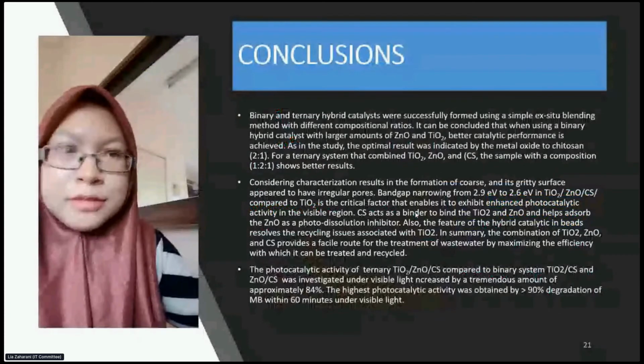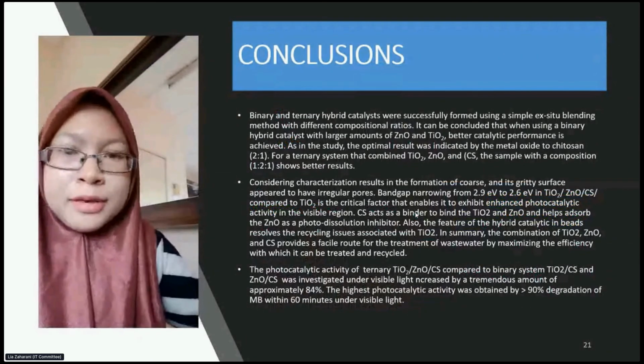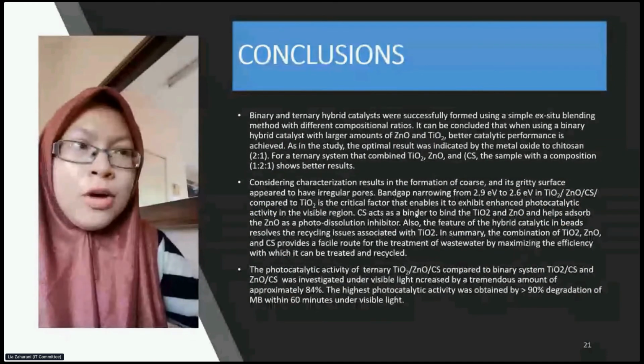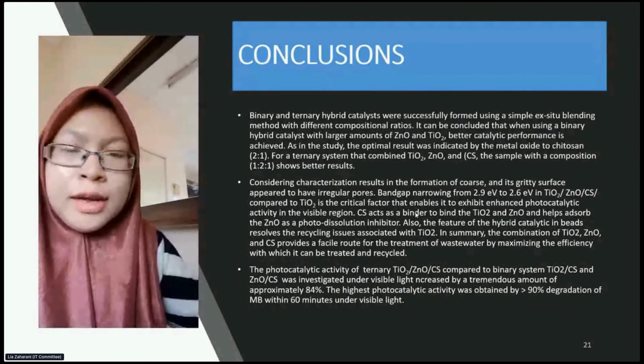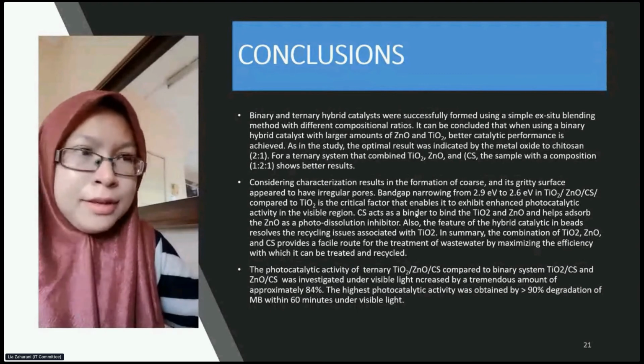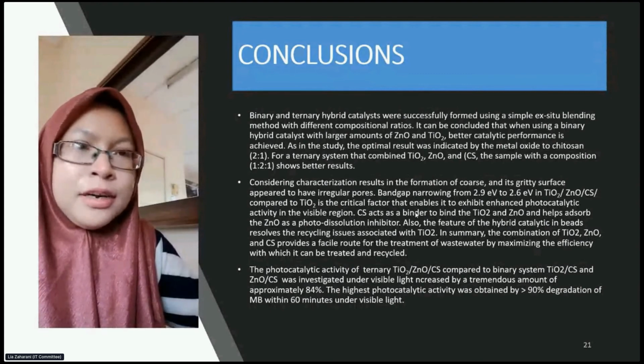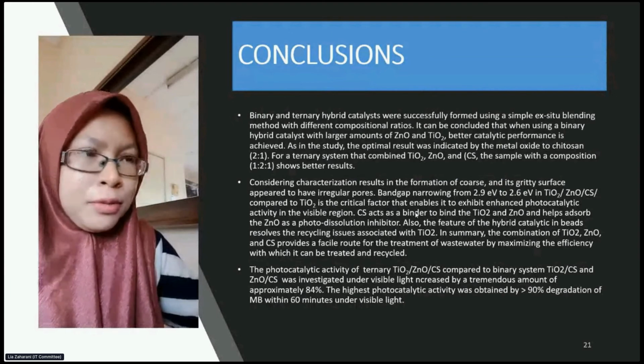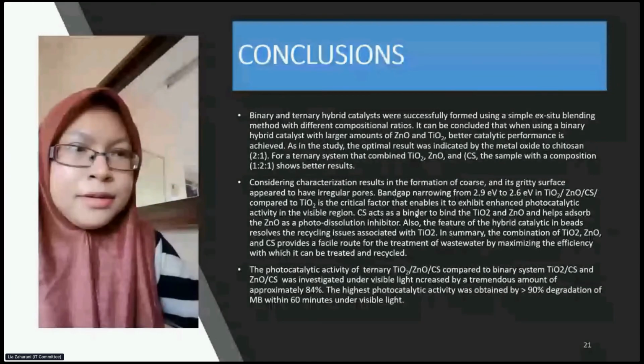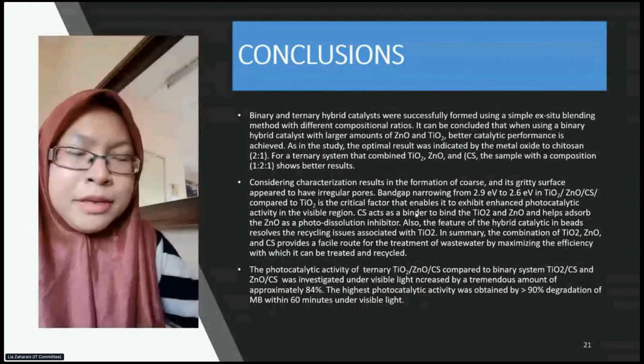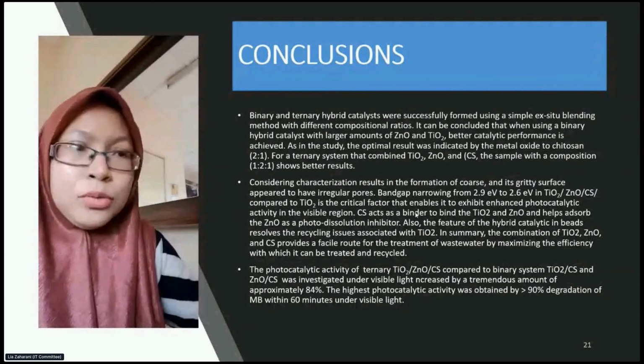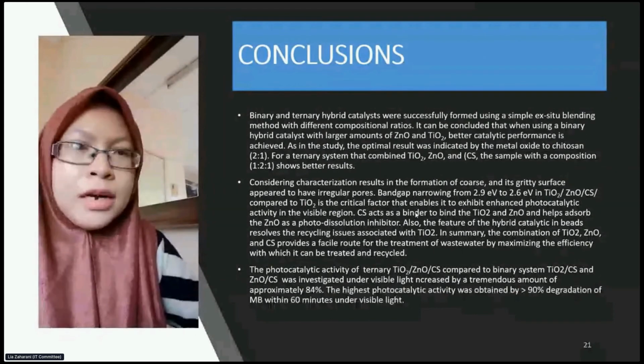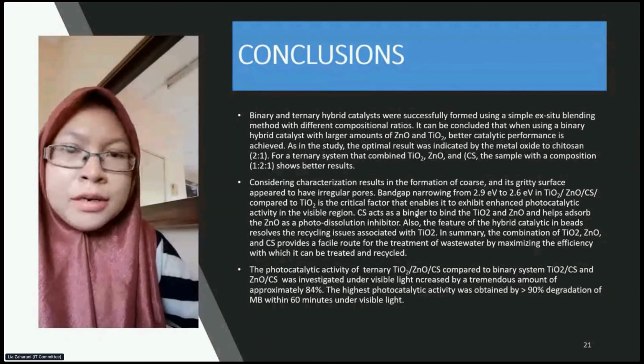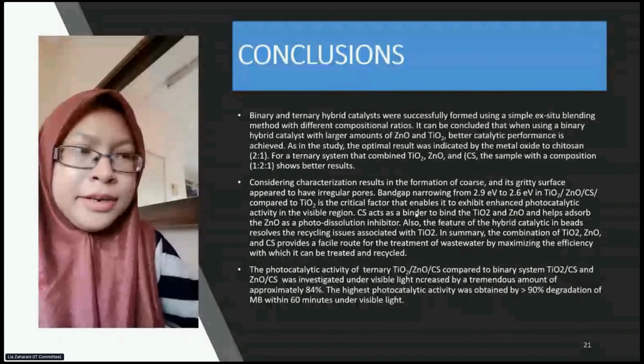As a conclusion, for this study, we have successfully produced the ternary system of the photocatalyst with different composition ratios, and it shows that the composition of 1:1 shows optimized results in terms of homogeneity, light sensitivity, and crystallinity. And considering the characterization results, the information of the core, its gritty surface appear to have irregular pores. Band gap narrowing from 2.9 to 2.6 makes sure that this photocatalysis system exhibits good performance in the visible regions.